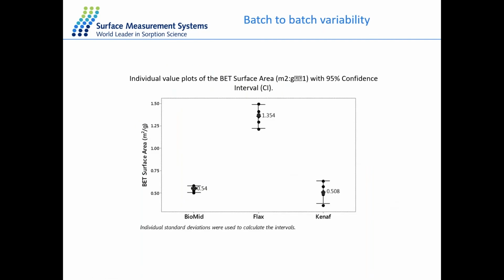We've also done some batch-to-batch variability studies as well, and what this is telling us is that looking at our processed fiber, we have a very small standard deviation across batches, again suggesting that because these fibers are processed, they are much more uniform. However, with our other two materials, we have a much larger variability from batch to batch. And this is a consequence of the natural fibers having some structural irregularities and being much more heterogeneous.